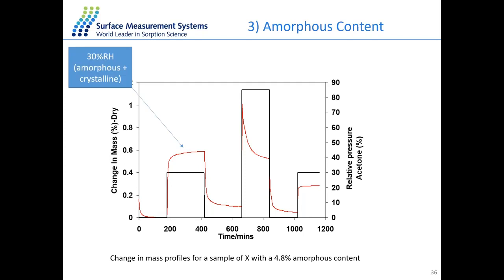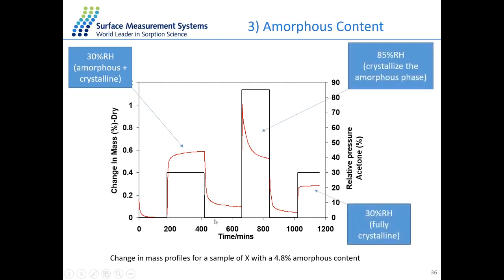So the next thing we do is we set up an experiment which has 3 different stages. Well, first is the drying stage, and we first set up with 30% relative humidity for the amorphous and crystalline material. So we know from our preliminary experiment that crystallization is induced at about 85% relative humidity. So we know that this is still in the amorphous state. So we carry it out over a certain length of time.